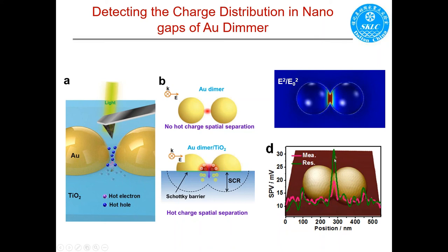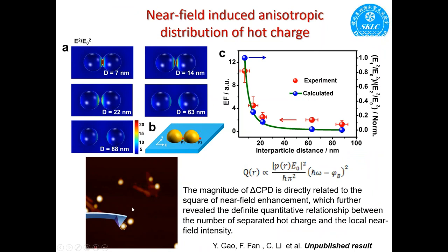This is at least an order of magnitude more than the single gold nanoparticles. You can use the AFM tip with the nano manipulation mode in Bruker machines to make different gold dimers. You can get a correlation between the charge separation and the local electromagnetic field. This is the first time that we show that the quantity of the charge separation is directly related to the square of the near field enhancement. That is to say, if you make more hotspots, you get more photogenerated charge and thus more efficient photocatalysis. So that's what we have done recently in the